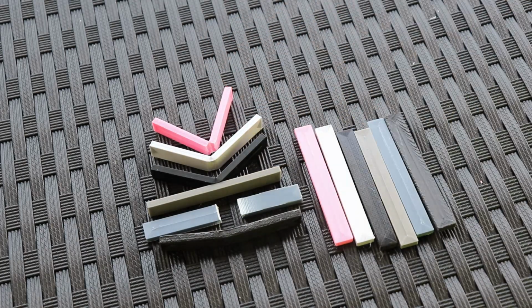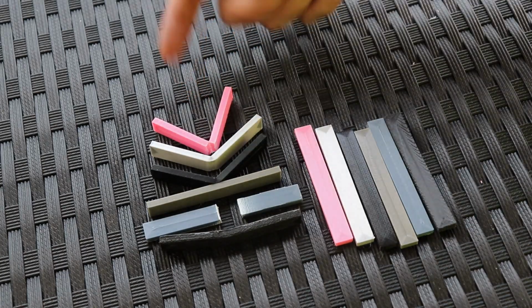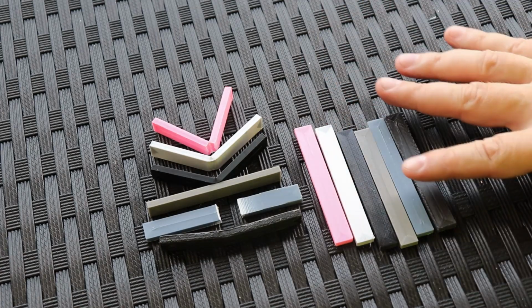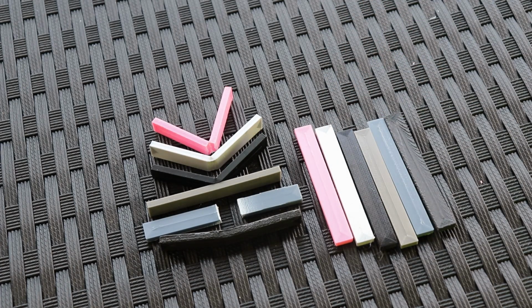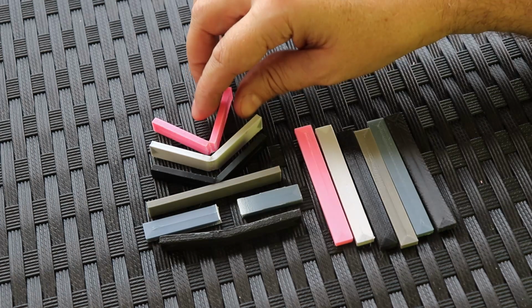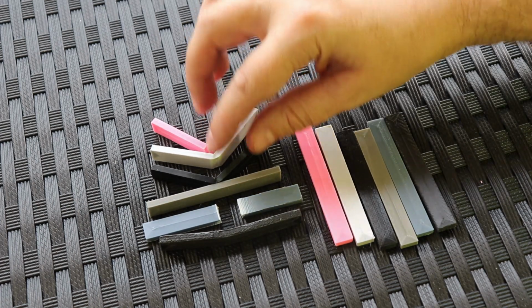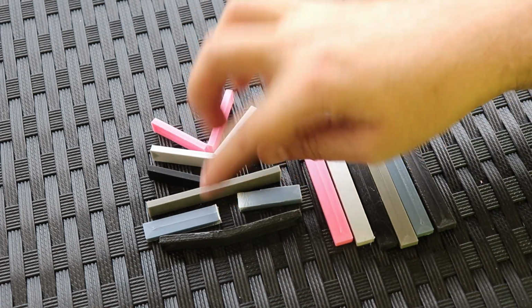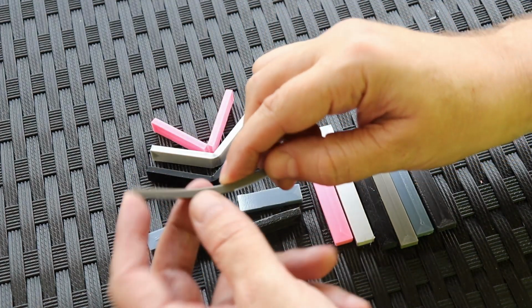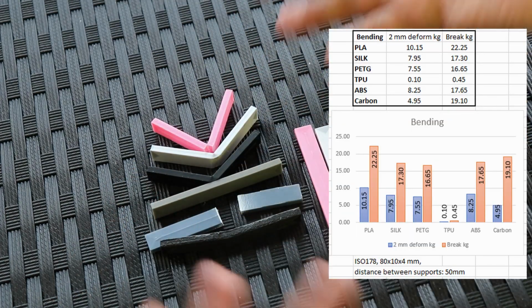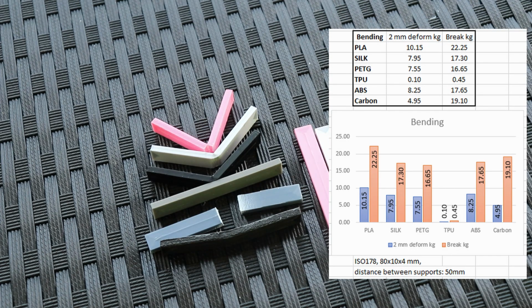This is the result of this bending test. I used only one test specimen because I have some plans with this one in the near future. And well, interesting that even the PLA didn't break, only ABS broke completely. On TPU you can't see any deformations, and in this table you can see summarized results.